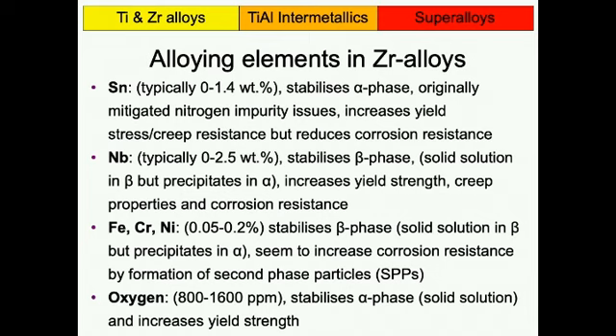And those additions, as you could see earlier in terms of Zircaloy-2, seem to increase the corrosion resistance. And it's often said it comes through the formation of second phase particles. Now you might have learned in other lectures that precipitates are not very good for corrosion or oxidation. Like in aluminium alloys, the precipitation strengthened aluminium alloys don't have particularly good corrosion resistance or oxidation resistance, right? So it's not clear why in zirconium these SPPs help. It's really not clear.